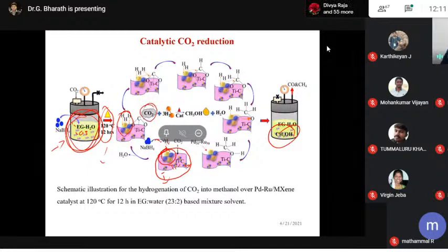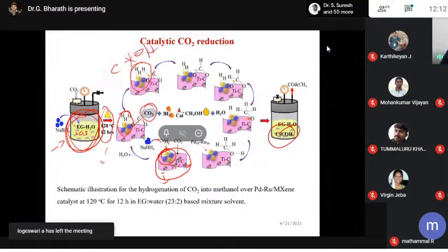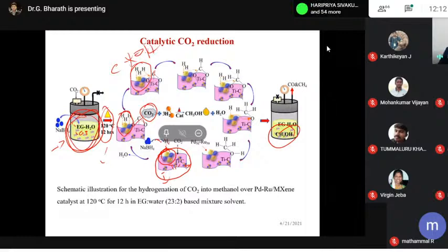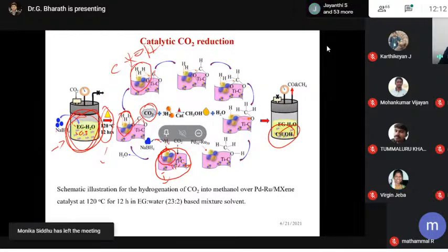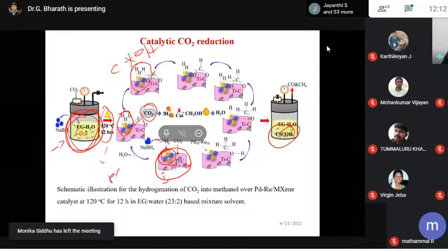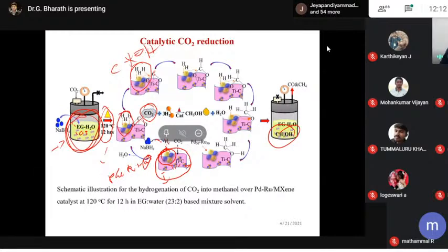And then you also have CO2. This CO2 easily attaches near this titanium carbide, and especially in this step, this metal hydride easily breaks the carbon-oxygen bond and inserts hydrogen. So this is the main aim. Here the titanium carbide captures CO2, and the metal hydride, actually palladium-ruthenium hydrogen, easily reacts with the CO2, breaks the C-O bond and inserts H. Through each reaction we finally get CH3OH from CO2. This is the final step.